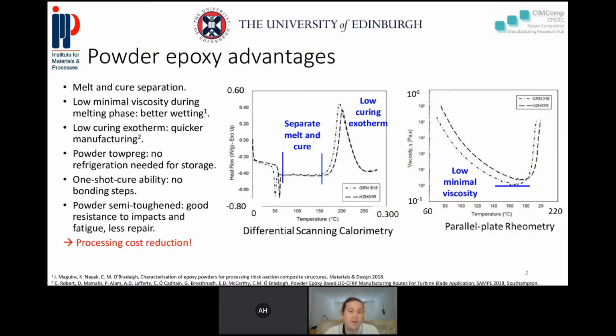So first, why would we use this powder epoxy technology? Well, if you have a look here on the differential scanning calorimetry graph, you can actually see that there's a small endothermic reaction showing the sintering and melting of the powder, followed by 100 degrees where nothing happens, and then the cure here. So what it means is the material, once melted, is completely stable at ambient temperature. It's heat activated. So that's the first thing. It doesn't need any refrigeration or storage.